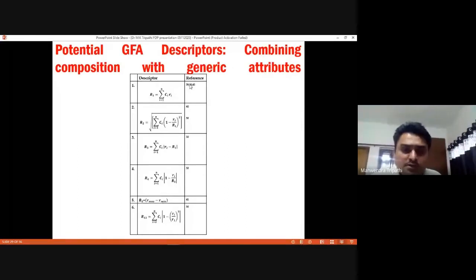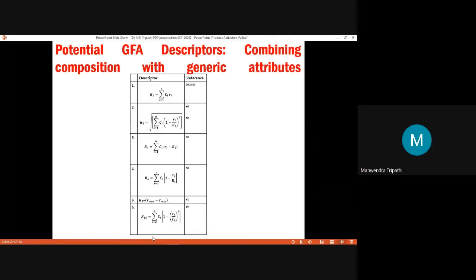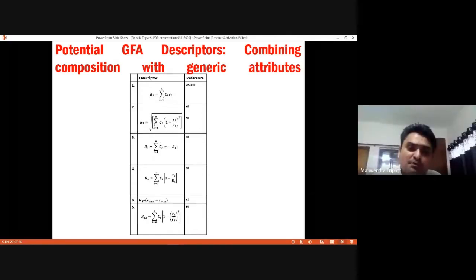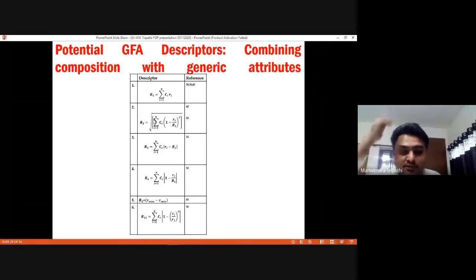In the literature, we have found that there are various ways, so we are converting the GFA potential into a GFA descriptor, using the composition and those generic variables, right? So we have tried such 13 variables, right? So basically, if you multiply 18 into 13, it comes out to be 250 such descriptors, right? So out of 250 such descriptors, which descriptor is significant? That was really a challenging task.